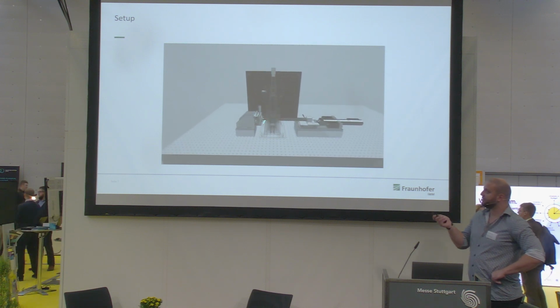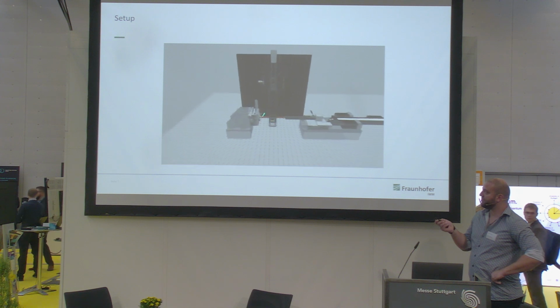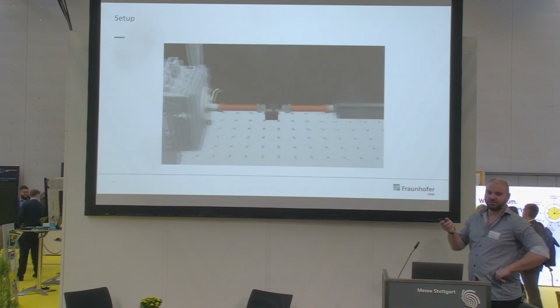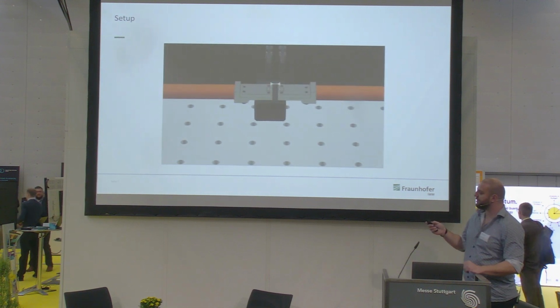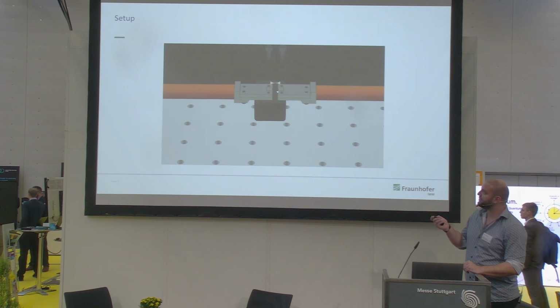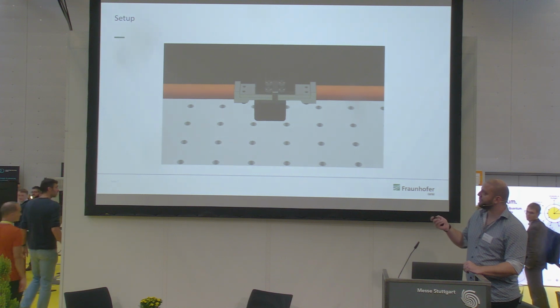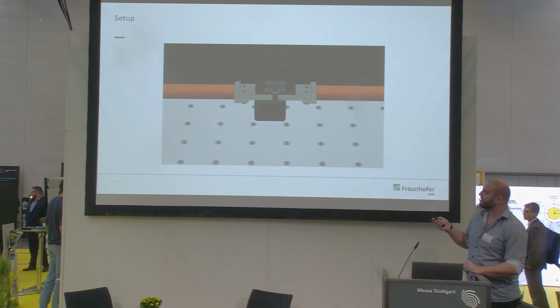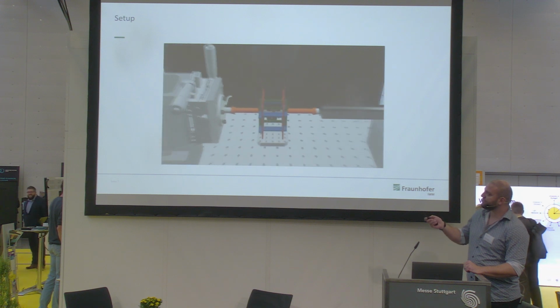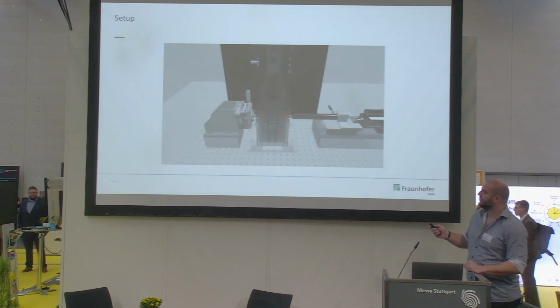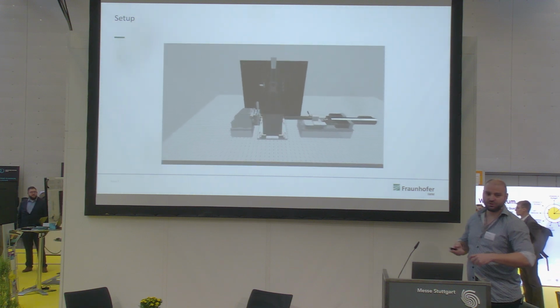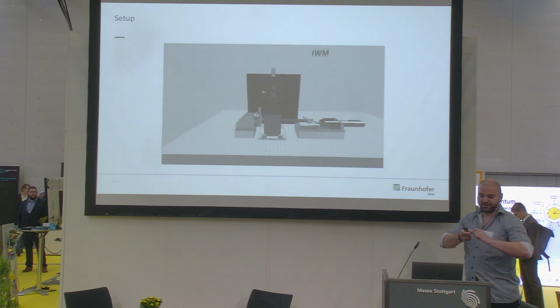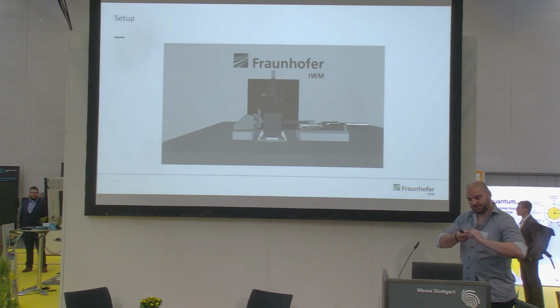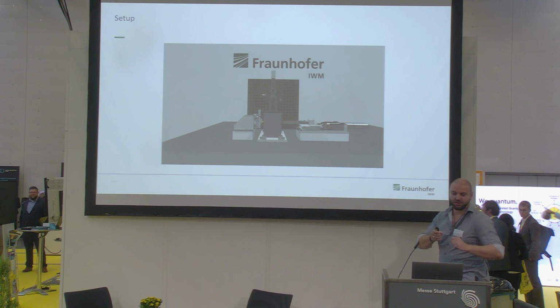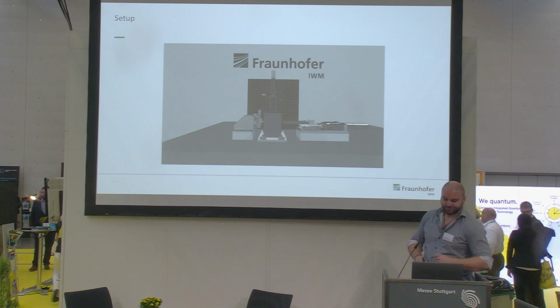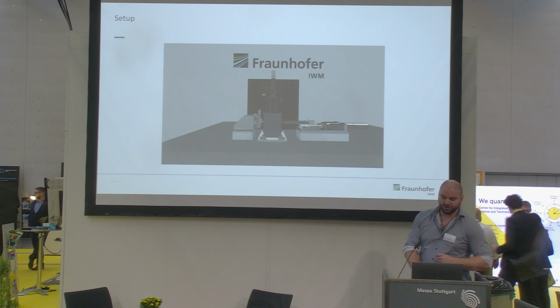And if you look inside of the shielding, we have a coil system which is used to suppress residual magnetic field gradients. And we clamp this sample here in the middle, and here is the OPM sensor. And when we pull this material apart, we generate the magnetic field, which is measured here. And on top of this, there's a camera in which we can measure the strain on the sample in a completely contact-free way by using a digital image correlation program.